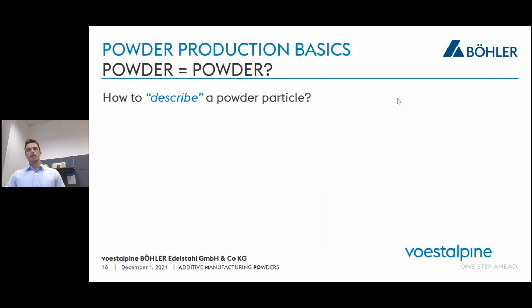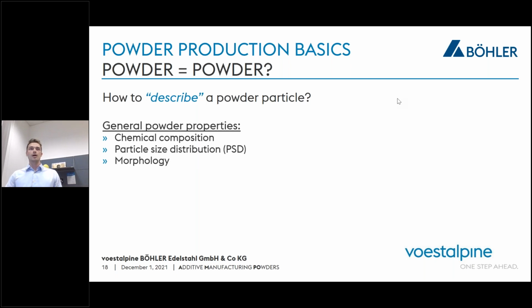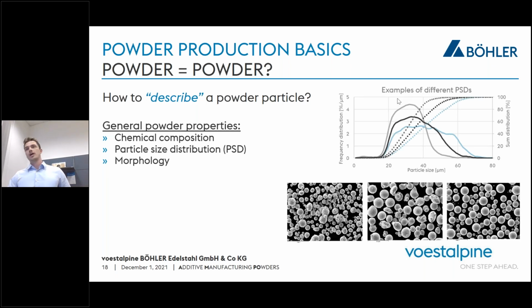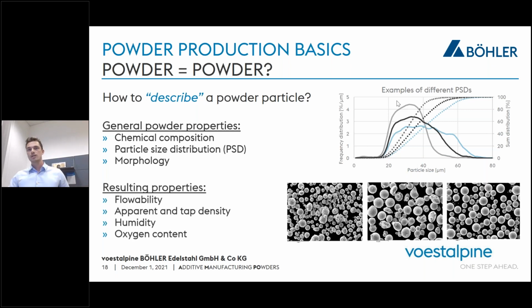So to give you an idea of how we actually describe a powder particle, there's the chemical composition, the particle size distribution, as well as the morphology. You can see on the right side we have the PSD on top, and then a few morphology pictures from SEM on the bottom. And this leads to our resulting properties: flowability of the powder, apparent and tap density, humidity, and the oxygen content, which we can measure as well.